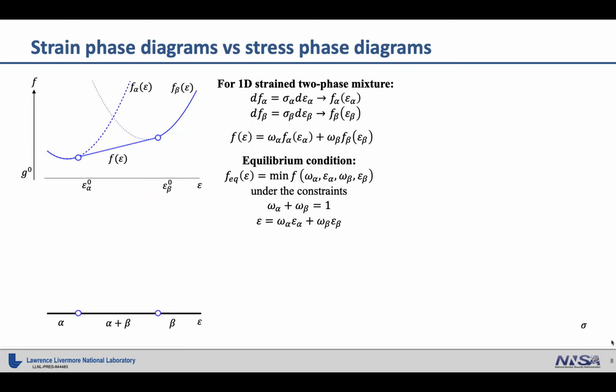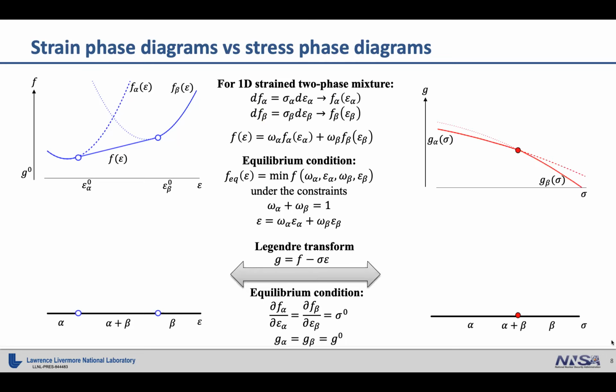And recently, we found another critical observation for this analogy, which is that the strain phase diagram and the stress phase diagram actually have a very close relationship. I will skip these equations, but the essential idea is if you start with the Helmholtz free energy as a function of strain, to predict the two-phase regions, you need to find the common tangent between the energy surfaces. But if you start from the Gibbs free energy in terms of stress, you just need to find the crossing point of the Gibbs free energy surfaces, which is a lot easier than finding the common tangent, especially for high dimensional strain space.